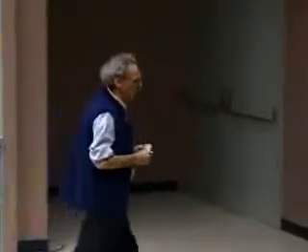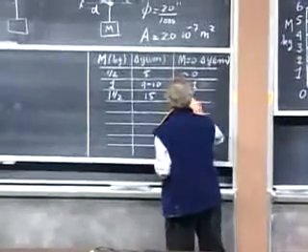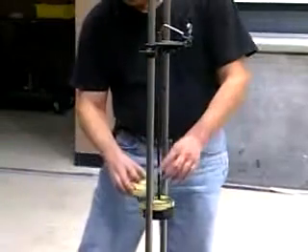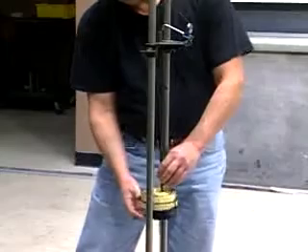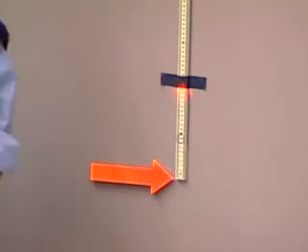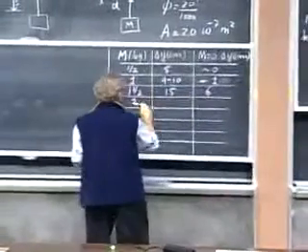Oh, but you see, it no longer wants to return to its original length. It's clearly longer now. Permanent deformation has already occurred. And so we are now at something like 6 centimeters. Can you make it 2 kilograms? Two kilograms. If it's linear, you would expect near 20. It's still amazingly linear. It's as close as I can see it to 20, but all these readings are no more accurate than half a centimeter or so.